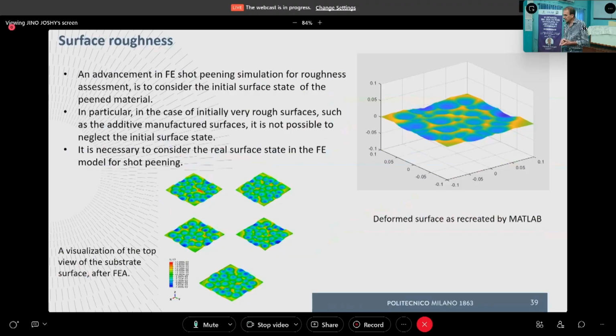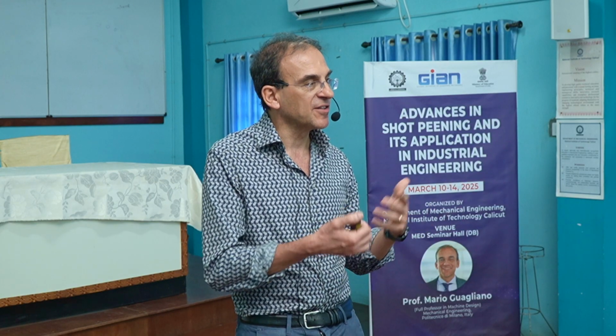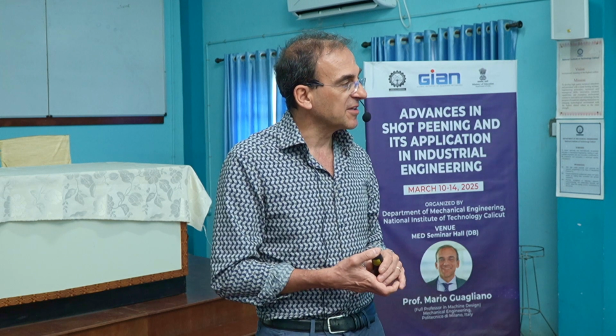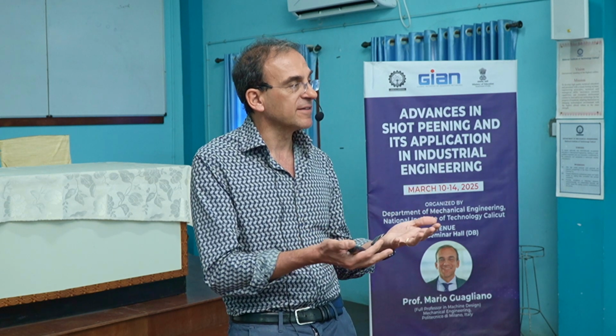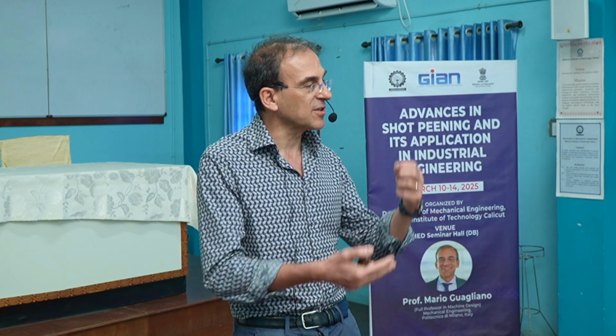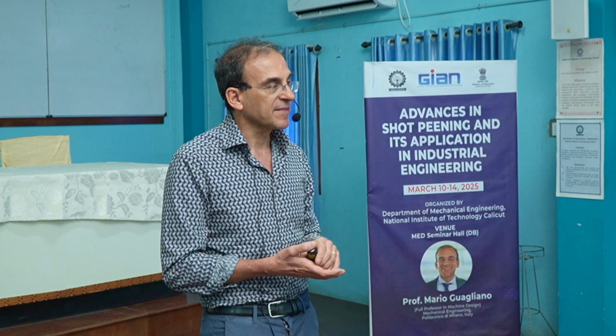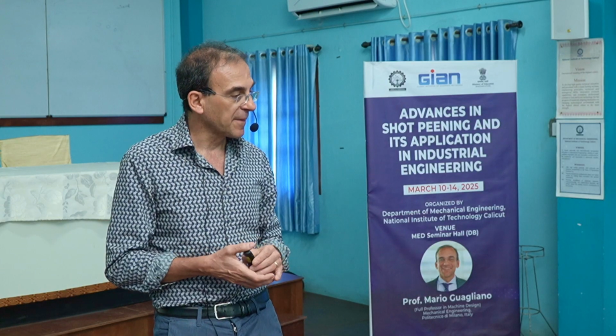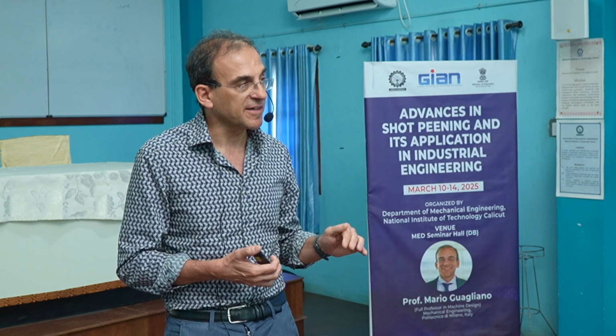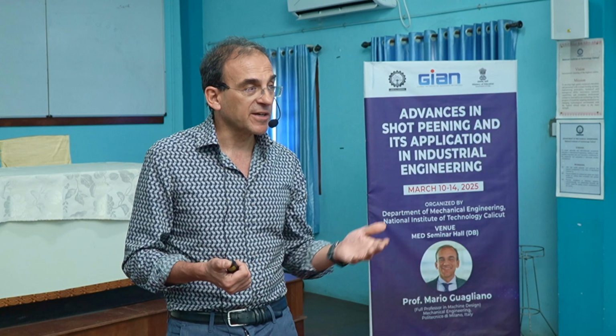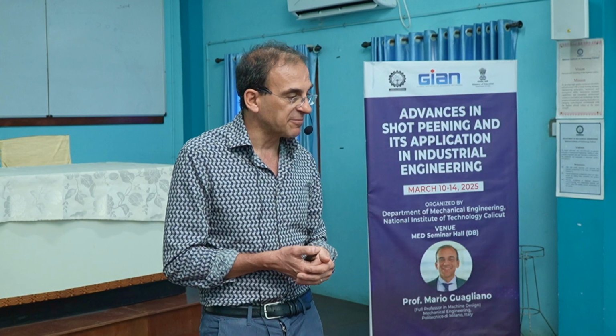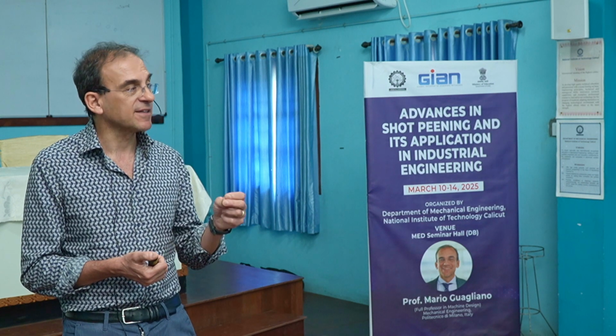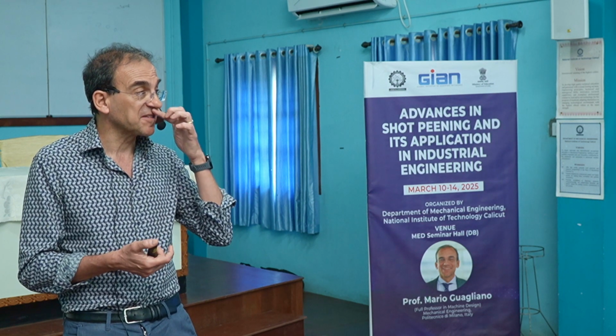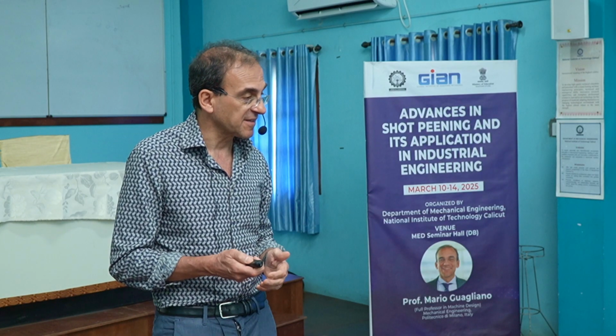And so, what can be done is that we can start from a digitalization of the initial surface before shot peening. After having the digital file, let's say the numbers, the file of this surface, we can use it as a base for defining the finite element model, and then start the finite element model of shot peening, considering the real digitalized surface as the input parameter. And in this case, the final result will be more accurate. And this is particularly useful, I will go deeper tomorrow, when we talk about additive manufactured parts. Why? Because we are starting from surfaces that have a very poor surface quality in those cases.